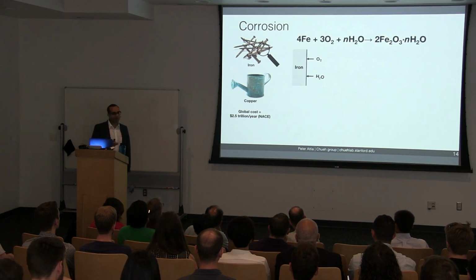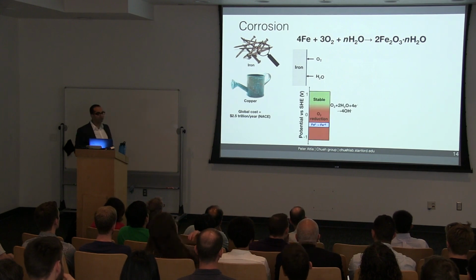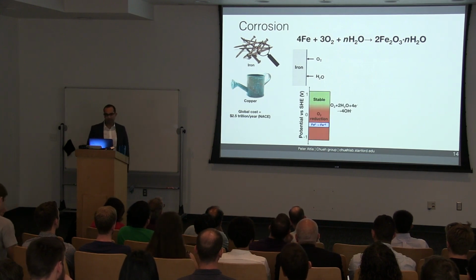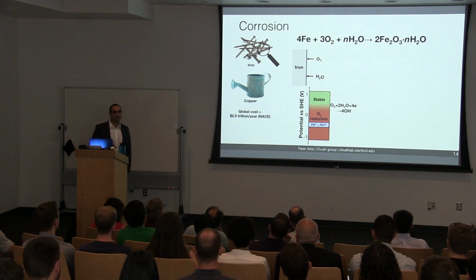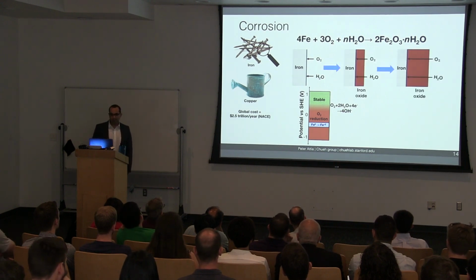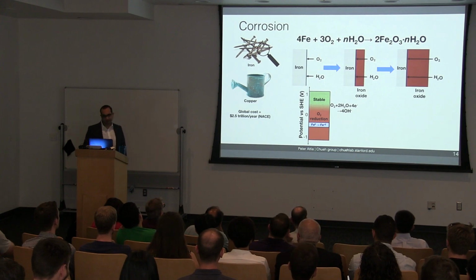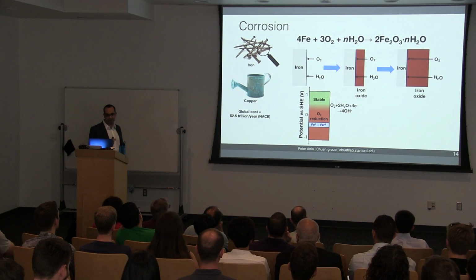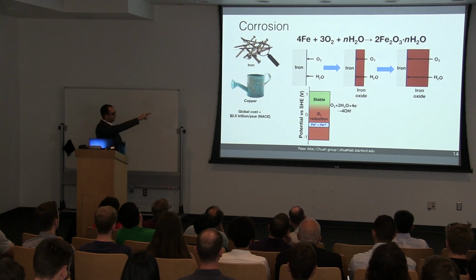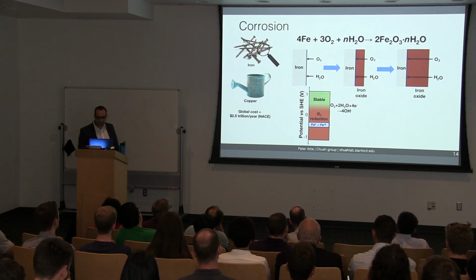Now, the rust reaction involves iron reacting with oxygen and water. This reaction occurs because there is a thermodynamic driving force for the iron to oxidize and the oxygen to reduce, just like there's a driving force for water to roll downhill. So some of the iron will convert and form iron oxide. As time goes on, this iron oxide layer gets thicker and thicker, which makes the iron thinner and thinner. For more rust to form, the oxygen and water have to first diffuse through the iron oxide layer for further reaction to take place.